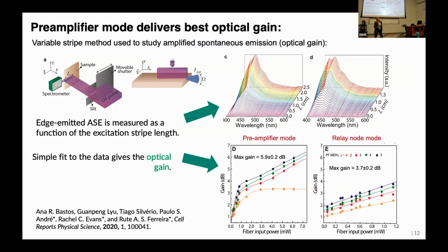What we found was, perhaps unsurprisingly, that the preamplifier mode gave the best result. We determined this by monitoring the edge-emitted amplified spontaneous emission, which is essentially optical gain that we get from the material. You just measure your sample emission at the edge using an excitation stripe of different lengths, and you look at the amplified spontaneous emission, and you get these spectra, and you can just do some data fitting, and this will allow you to get your optical gain. What we see is for the preamplifier mode, we get an optical gain of around 6 decibels, but in the relay node configuration, it's about 4 decibels.